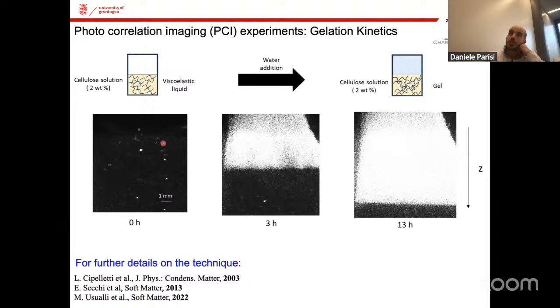So here, everything is dark, and this is basically at time equal to 0. So there was no water. Then we insert water, and then you start seeing all this multispeckle popping up. This is basically the interactions of water with the solution, and this is basically how the gelation front moves inside the sample. So this is the part where the solution is in contact with water, and this is basically the bottom of the capillary. So after 13 hours, almost the whole solution becomes a gel.